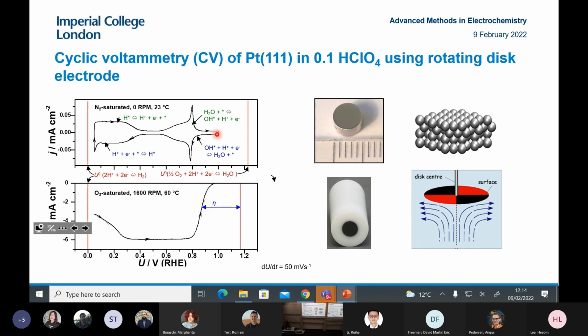So there's no irreversibility, which is different from if you look at nanoparticles of platinum. You usually see that these peaks are somewhat asymmetrical. And so then when we put oxygen into the cell, we start to see a current. You can see the current is a lot larger than it is here. And this is because we've got oxygen reduction taking place.